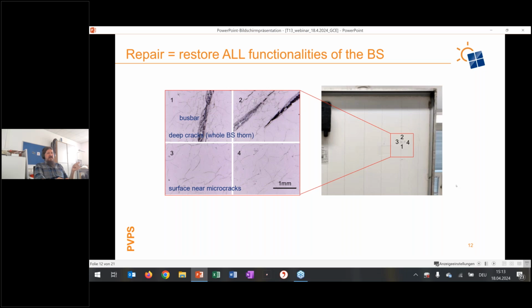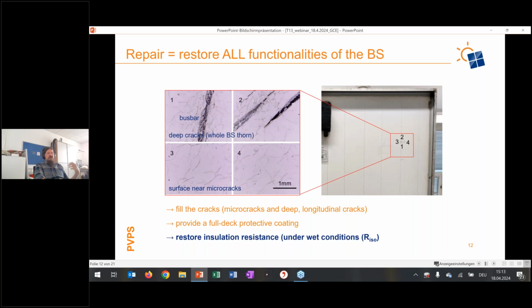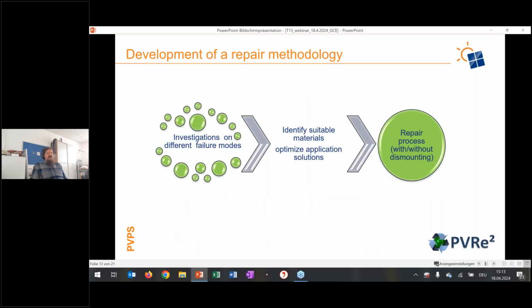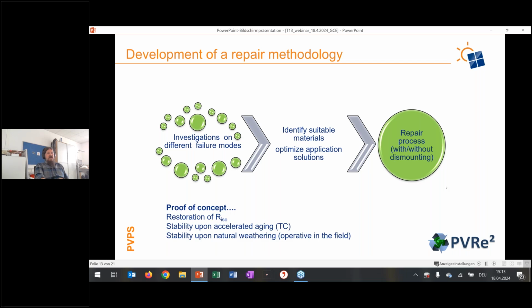And how could we possibly repair this backsheet? We need to restore all functionalities, meaning we need to restore the barrier, we need to restore the electrical insulation, we need to fill the cracks and provide a full deck protective coating in order to do that. So how did we do that? In a project called PVRE, we started with the investigation of the different failure modes, so we know what happened, and to identify if it's repairable or not. Then we identified suitable materials and application methods for the coating, and then we started repair trials with and without dismantling of the PV modules. Within the first project, we made a proof of concept that the restoration of R_iso, the electrical insulation, is possible.